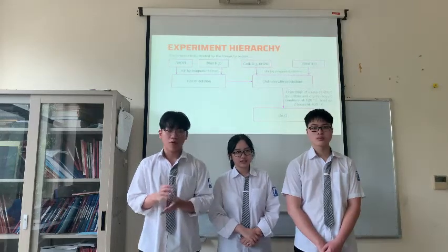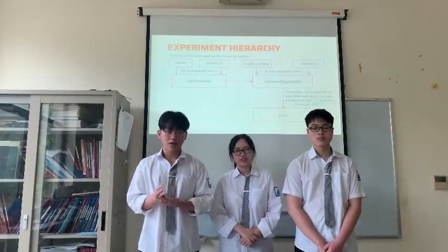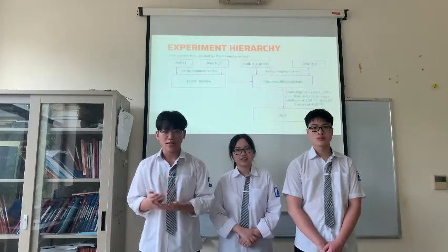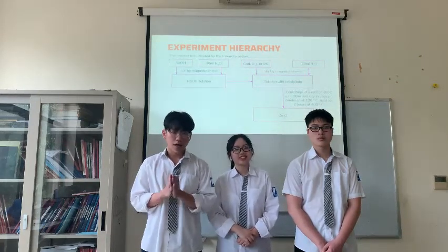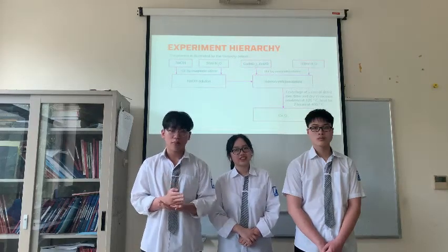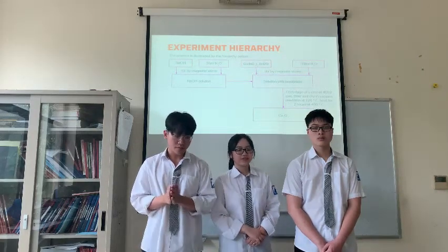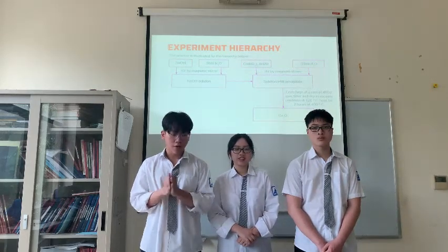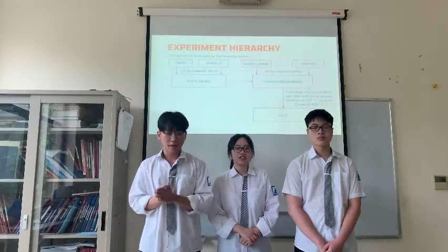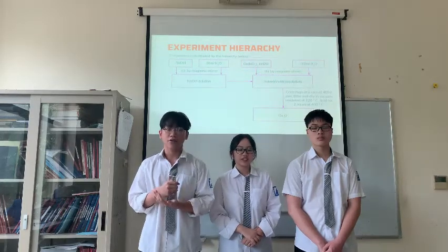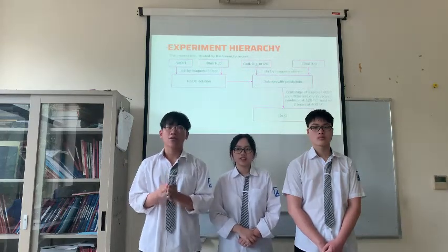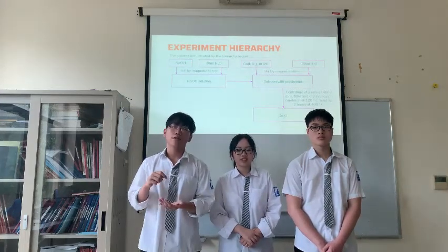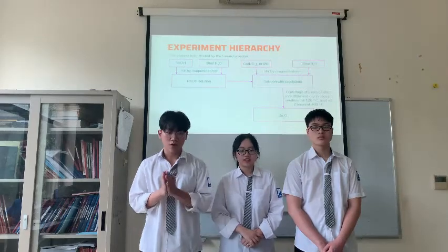In the third step, we're going to pour the sodium hydroxide with water into the bottle of cobalt nitrate hexahydrate with water, and then precipitates containing nanoparticle cobalt oxide are formed. We centrifuge the solutions at a rate of 4,000 rounds per minute, and then filter and dry in vacuum conditions for 2 hours at 100 degrees Celsius before heating them at 400 degrees Celsius for 2 hours.